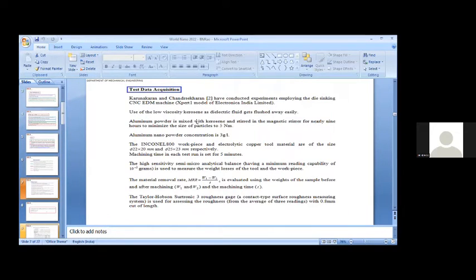Then low viscosity kerosene is used as the dielectric fluid. They have mixed aluminum powder with the kerosene and stirred it in a magnetic stirrer for nearly 9 hours to minimize the particle size to 5 nanometers. So the aluminum nano powder concentration is 3 grams per liter. The workpiece is 22 mm in diameter and 20 mm in length, whereas the copper electrode is 25 mm in diameter and 23 mm in length. These are the sizes they have used.